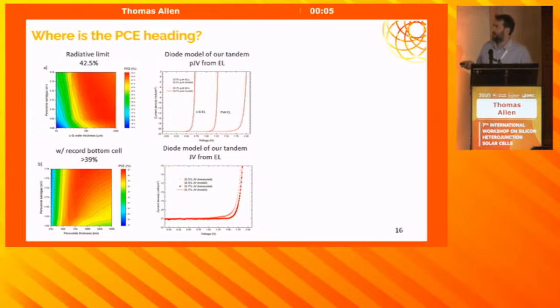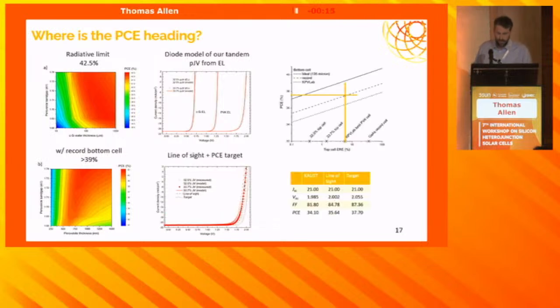That is almost completely suppressed in the 37.5% cell, and with some drift diffusion simulations, I think it's likely a result of a suppression of the mobile ions in the perovskite to something that's now almost negligible, at least in having its impact on the JV.